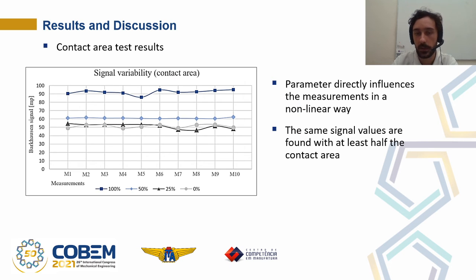When evaluating the average of the values as a function of the contact area of the sensor with the surface, it is noticed that the parameter directly influences the measurements in a non-linear way. This is observed when comparing the values of the sensor completely in contact with the surface with the measurement values with the sensor completely blocked, whose value is not null, representing 56% of the total value on average. So it is found that having control of the contact area of the sensor on the sample is a very important parameter, showing that the signal may drop in half when not having the ideal position while measuring.